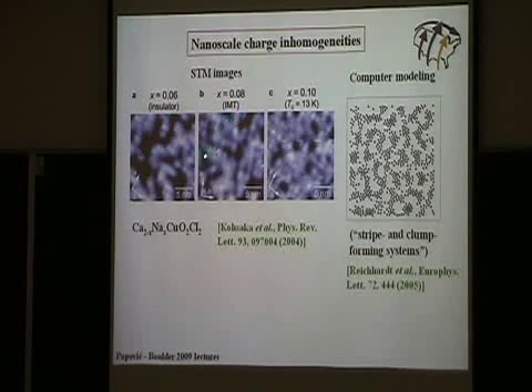These are STM images of one material for 3 different values of doping. At low doping, this is an insulator, and then here it's already a superconductor. And the white areas show the charge distribution in this material. So you can see that it is very inhomogeneous. Even when it becomes a superconductor, it is still inhomogeneous. There are still some areas where there is no charge. Also, there are some appropriate computer models which show that the charge distribution is inhomogeneous.